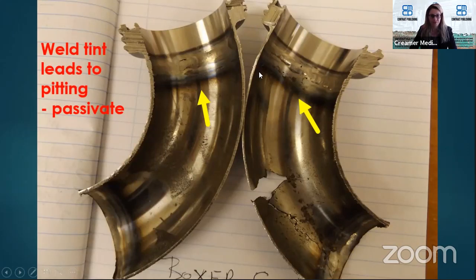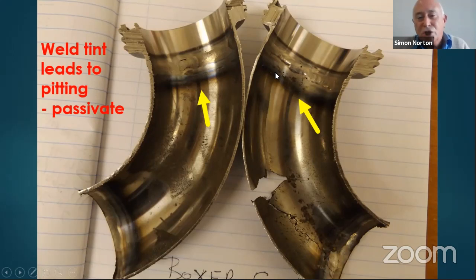Yeah. This particular photograph shows what happens when they did not shield the welding correctly. And you can see the heat tint at the arrows. Where that heat tint occurs, it will extract the chromium into the oxide layer and weaken the stainless steel. It loses its ability to be stainless steel, essentially. So the critical thing, ignore the cracks at the bottom. That's not relevant to this particular person's problem.